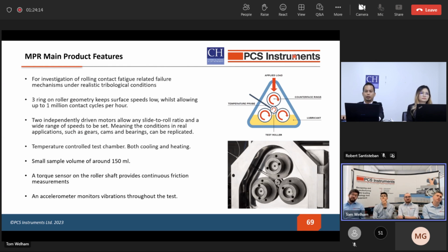The discs and the rollers are driven separately, so we can generate slide ratios. It is temperature controlled, so we can raise the temperature up to 135 degrees Celsius. And we have lubricant in the sump. As the discs are spinning around, this lubricant is splashed around the entire chamber, ensuring that sufficient lubricant is entrained in the contacts at all times. There's a torque sensor on the roller shaft, which allows a continuous friction measurement, and we have an accelerometer mounted onto the top shaft of the disc, which gives us a monitor of the vibration, which is really useful for investigating fatigue, where vibrations have quite a large impact on the type of damage that we'll see.